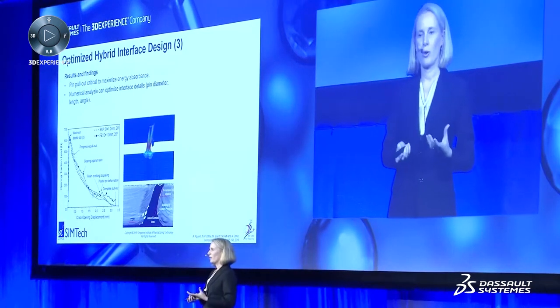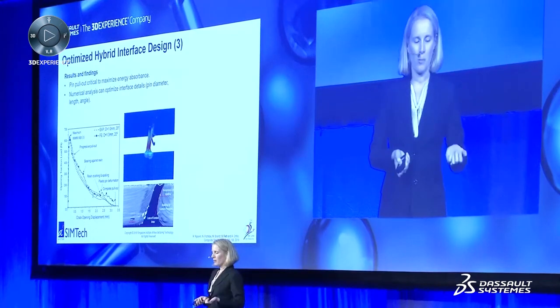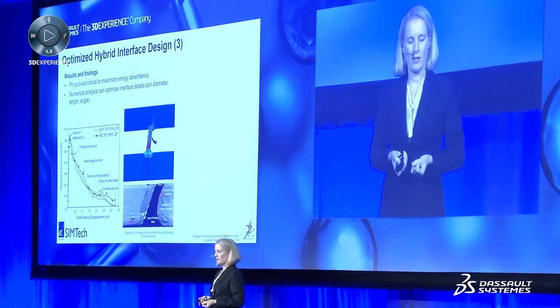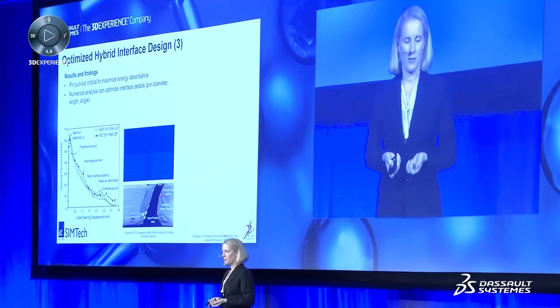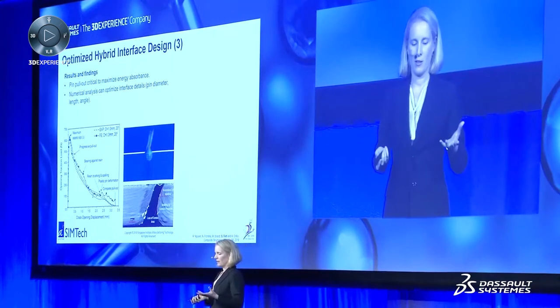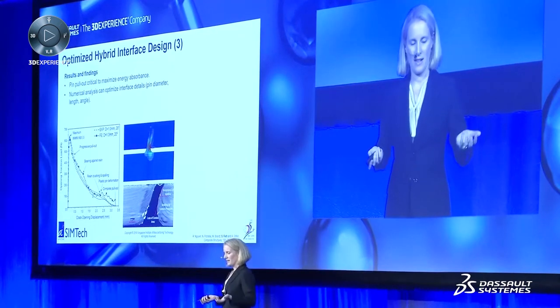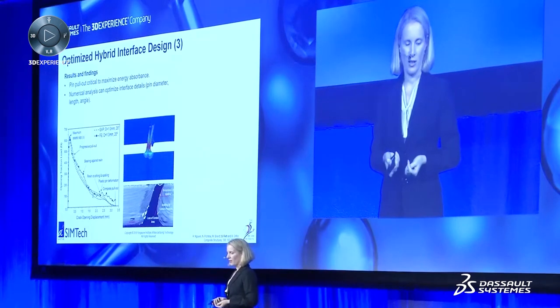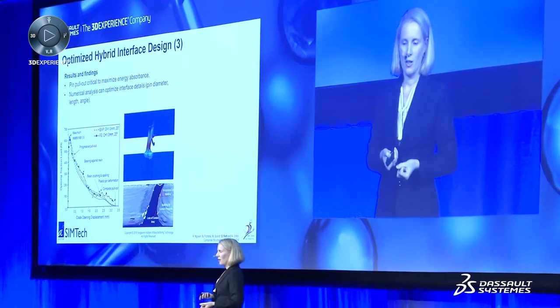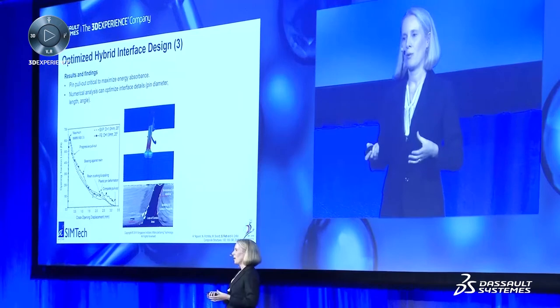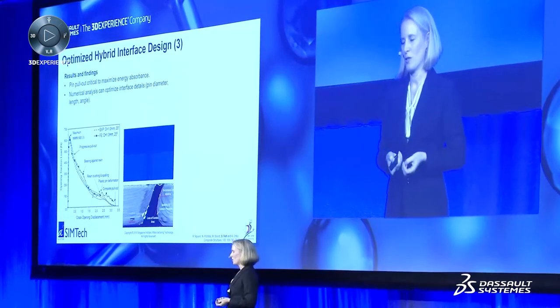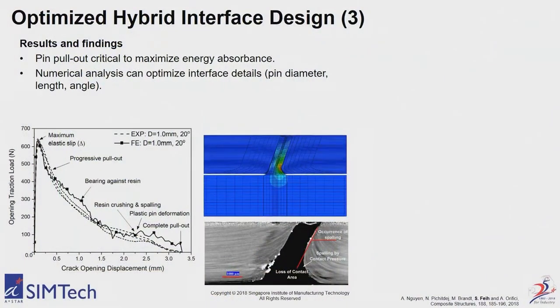And again, there are a lot more things we can pick up from the FE model compared to the experiment. We can see that initially we have progressive pullout of the pin, depending on the angle. Then we have bearing against the resin, then resin crushing, and plastic pin deformation, and all this contributes to the pullout mechanisms and the energy absorbed during pullout. So, much more than we can actually get from our experiment.